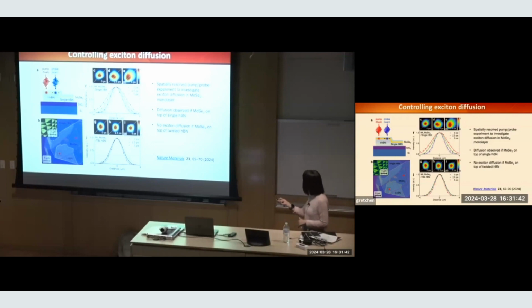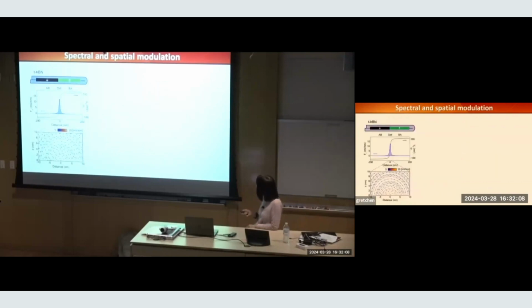So we didn't understand what it's really doing to the TMD by the time we published this paper. We were forced to add this data. Reviewers asked for it. We're like, okay, let's put something in that we don't quite understand. What we don't understand is we actually see a complicated spectrum for the excitons. We just showed you the image, which shows the confinement, but there's a lot more happening. Since then, we've understood a little more.